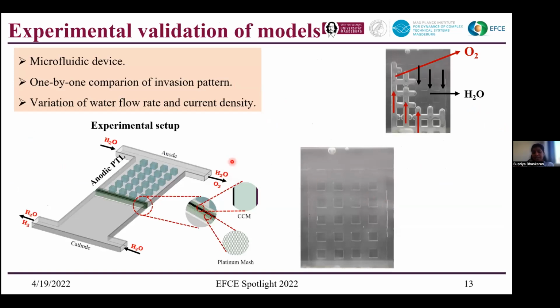So as I said at the start, all these models require an experimental validation. So for this purpose, we have a microfluidic device, which is made from a PMMA material. So here is the schematic representation of our experimental setup. Since our major focus is on the porous anode side, we have made the anode porous transport layer as a homogeneous distribution of pores and throats. And the cathode, since it's not the major focus, we have just kept it blank. And between the anode and the cathode, we have the CCM coated membrane. So we have the membrane coated with the anode catalyst as well as the cathode catalyst.